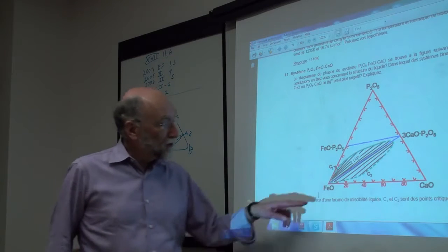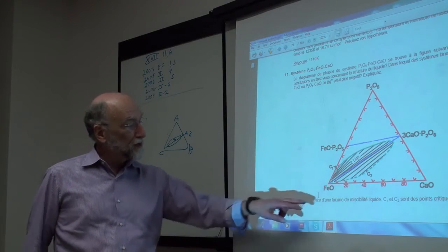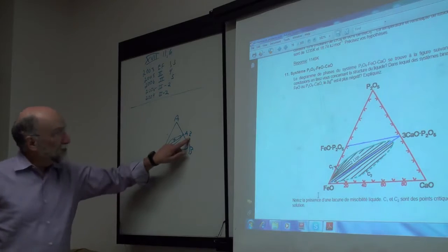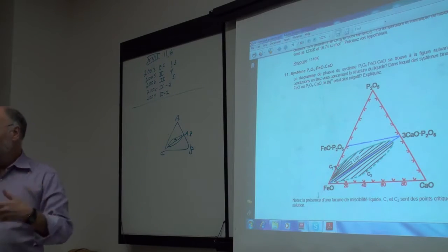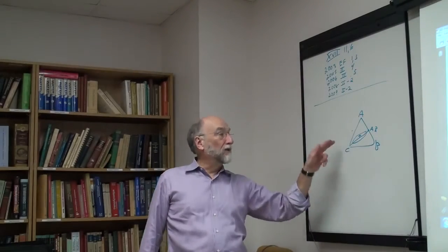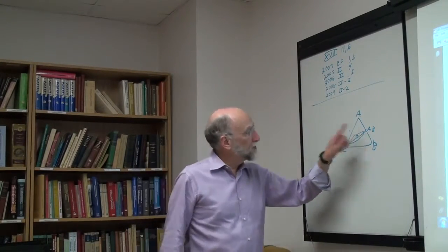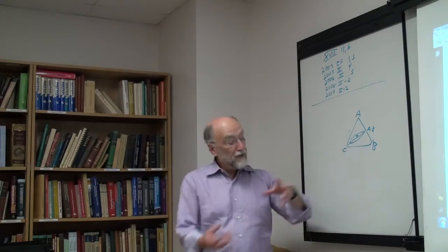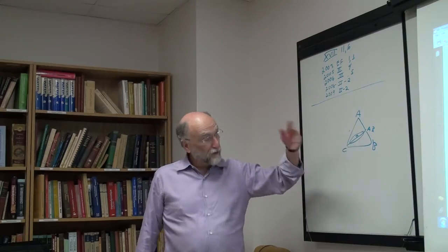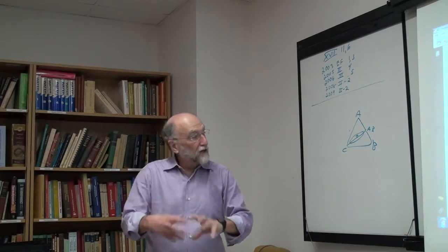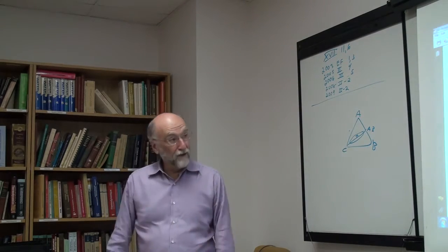Even if you don't have short range ordering, even if it was a random Bragg-Williams mixture, as you're adding C to AB, you're breaking up the strong AB bonds. Actually, I showed before that if you have Bragg-Williams mixing, you actually overestimate the positive deviations because the A's and B's can't even cluster. You're just breaking them up. If you have short-range order, they can actually cluster within the single phase and lower a little bit. Anyway, but you always see these things.